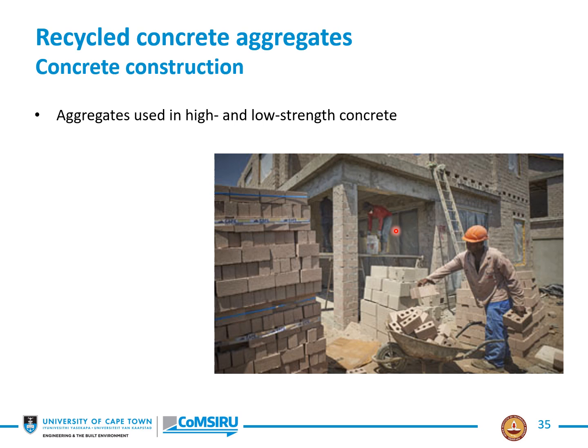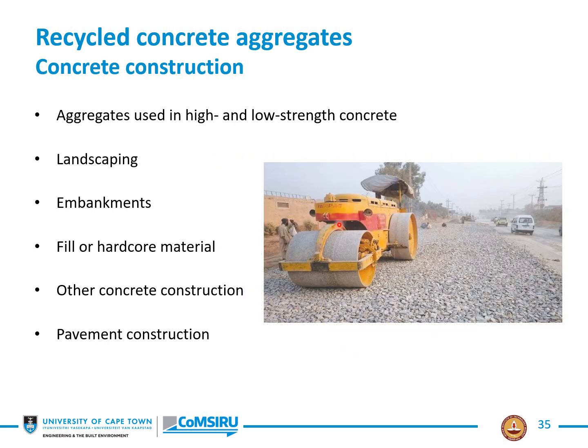This is an eminently useful and suitable use for these materials, because here the strengths are lower and therefore quality is less important, although of course not unimportant. But bear in mind there are other possible uses: landscaping, embankments, fill or hardcore material, other construction, or pavement construction. And here you see an example of a road base from recycled concrete aggregates, where they're going to put the topping layers on there, and this is very acceptable if it's okay with the standard.